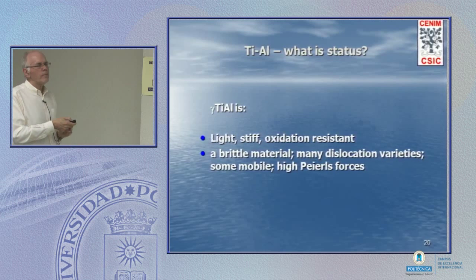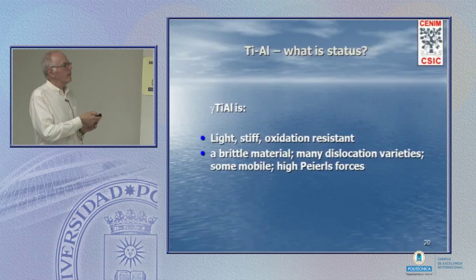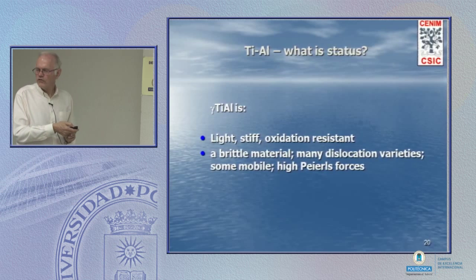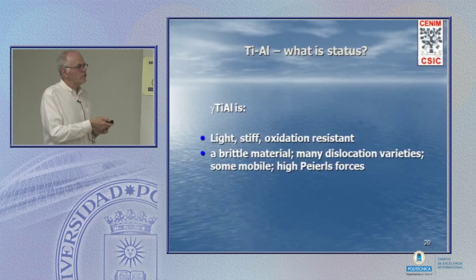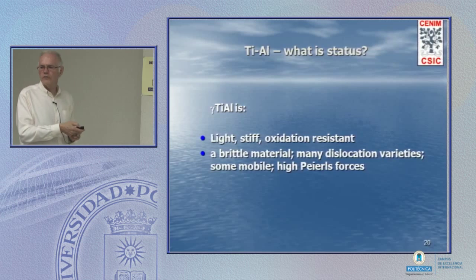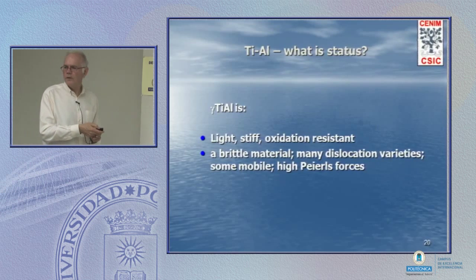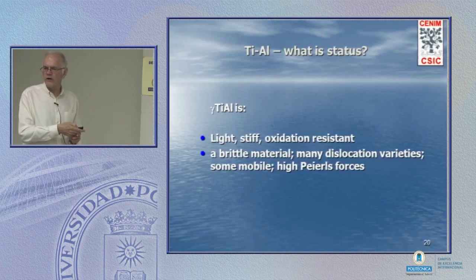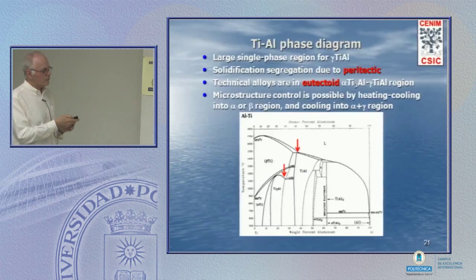First of all, the gamma TiAl, this is a light, stiff, oxidation resisting material, but it's also brittle. There are many dislocation varieties. They're not all terribly mobile because of the Peierls stress problem. Here's the phase diagram of titanium, aluminium. Here's the TiAl region. It exists over a fairly wide composition range, and exists ordered up to the melting point.